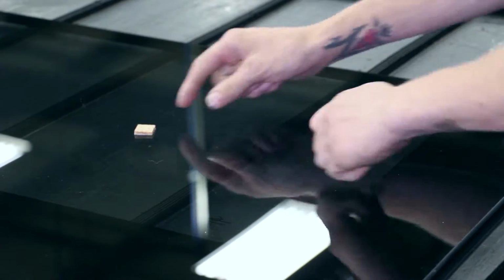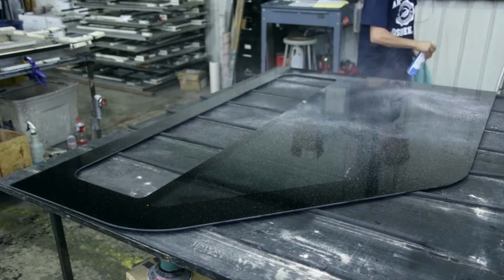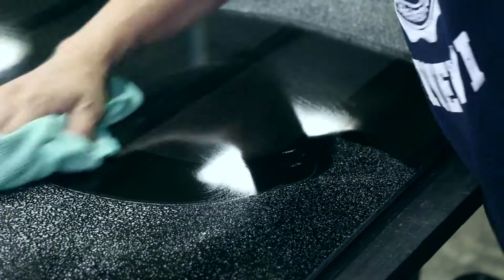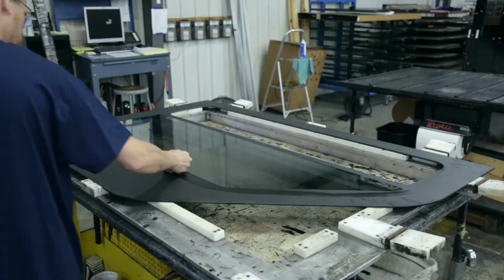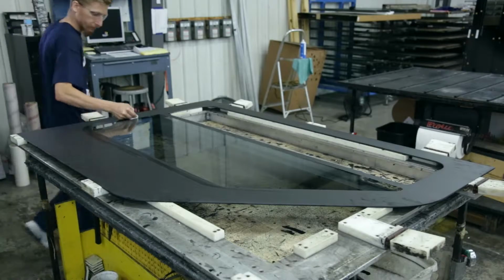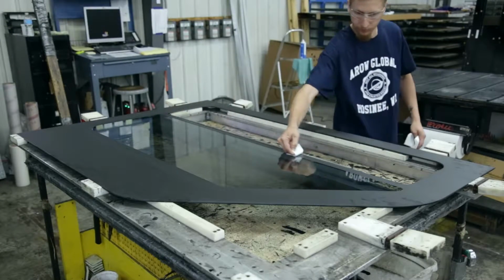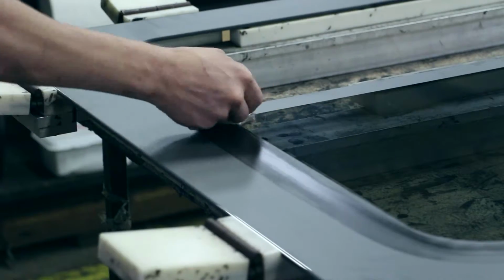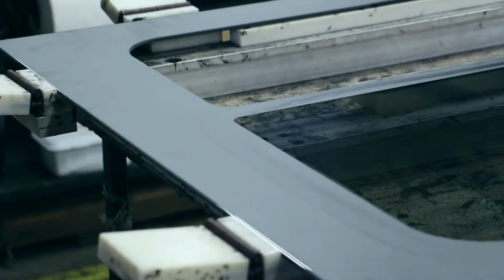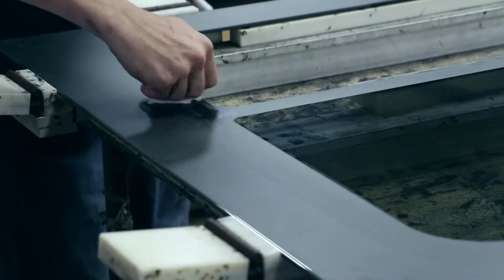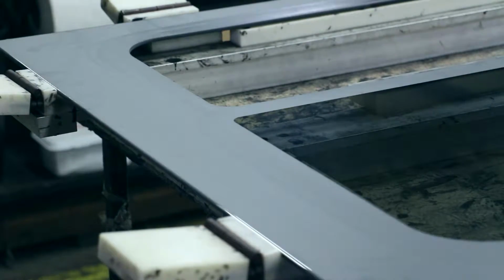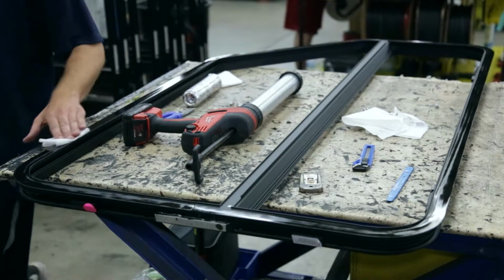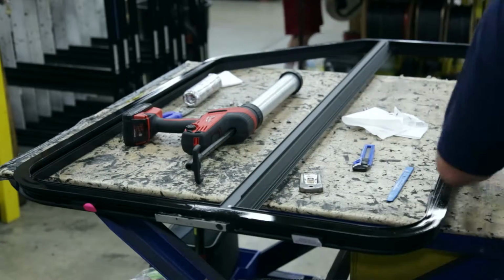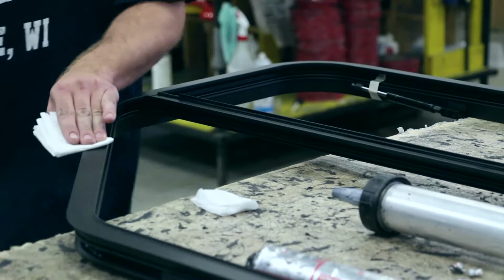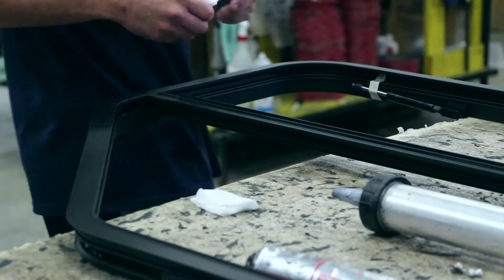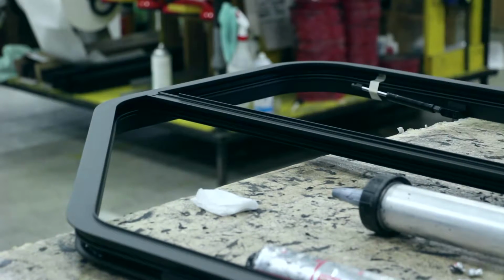Step 2. Remove any protective shipping material and clean the surface of the glass with glass cleaner. Step 3. Clean all bonding surfaces, glass and frame, with isopropyl alcohol. When cleaning, make sure to wipe in the same direction so that contaminants are not transferred from one area to another. Complete the cleaning with isopropyl alcohol at least 3 times, using a clean cloth with each round of cleaning. All alcohol used for cleaning the bonding surfaces must be completely dried prior to applying adhesive. Contact between the alcohol and adhesive will prevent the adhesive from curing.